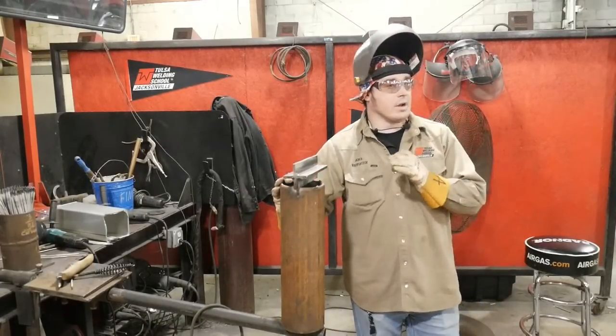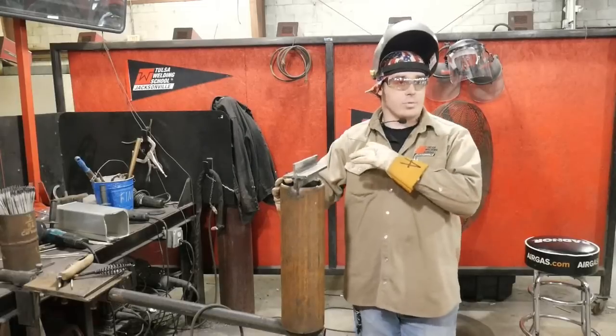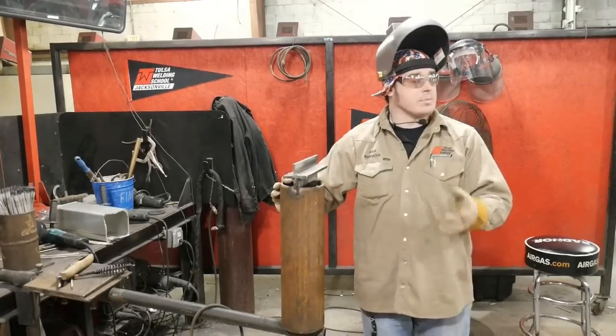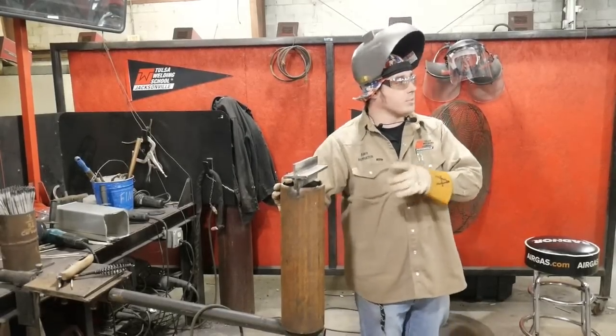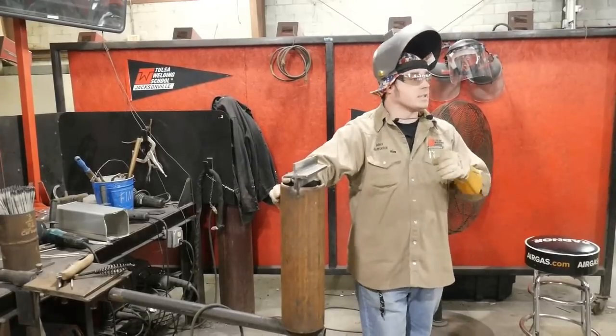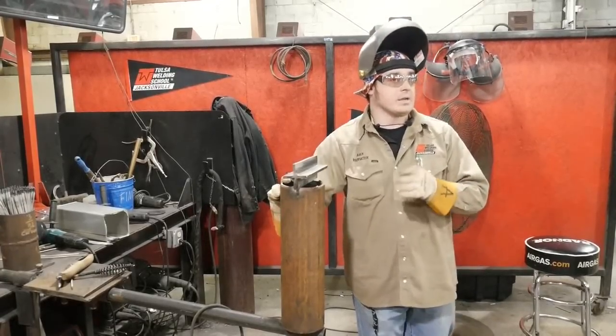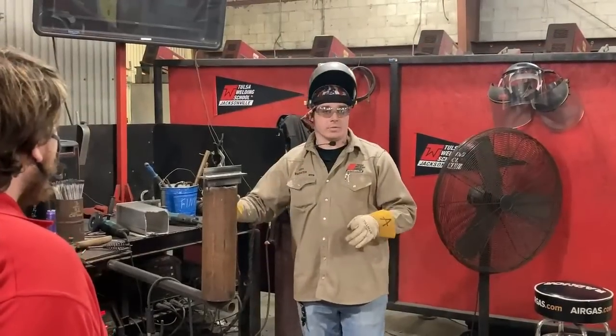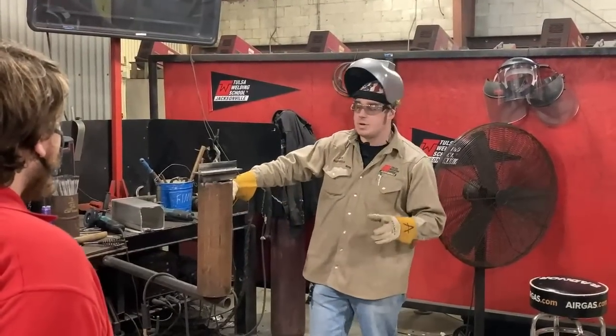That's removing an unwanted amount of material. So as you're welding, you're putting down material, but if your base metal is too hot, you'll be removing your base metal, and that's what we call undercut, okay? So we put it in the quench tank, we can relieve ourselves of undercut sometimes, most of the time.